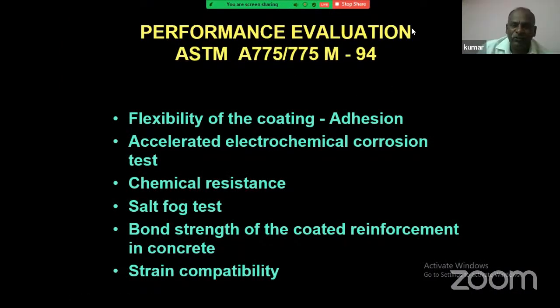The performance evaluation has to be done with the ASTM standard, which is ASTM A775/A775M-94. So what is the evaluation of the coated steel? You have to find the flexibility of the coating by bending, and the accelerated electrochemical corrosion test, called the 2-volt impressed voltage test, we have to conduct. Then the chemical resistance test, then the salt fog test in the salt spray chamber. And the bond strength of the coated reinforcement: the bond strength here is 1.2 times, that means 120%. And strain compatibility we have to check, with respect to the stress-strain relationship, that the strain compatibility of the coated steel is on par with the uncoated steel.